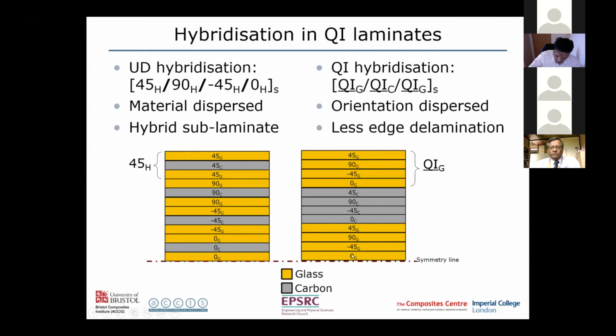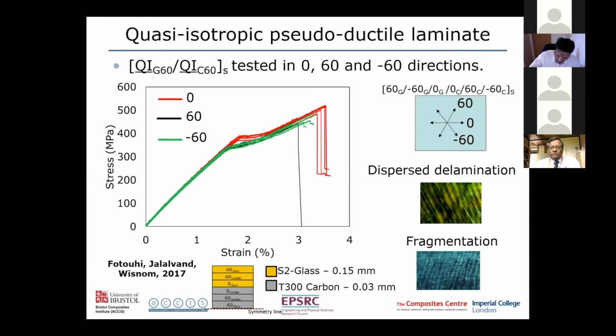Both methods work and have different advantages and disadvantages, but generally this one we think is better, the orientation dispersed, because it produces less edge delamination, which can be another critical failure mode in composite structures. So you see with this quasi-isotropic laminate, this time it's a 0 ± 60 layup, we see the same pseudo-ductile response with a bit of a plateau, additional strain, and we can load this in any of the fibre directions and we get a similar response in each of the directions.